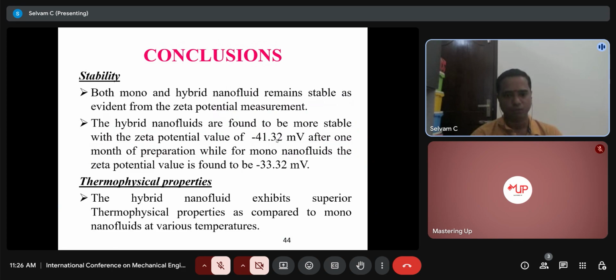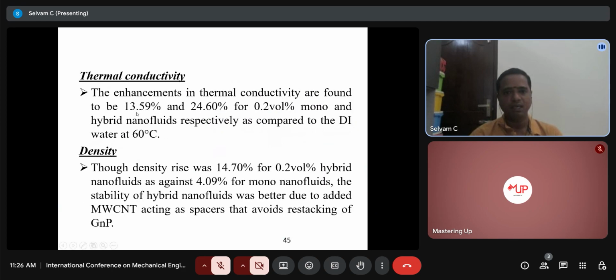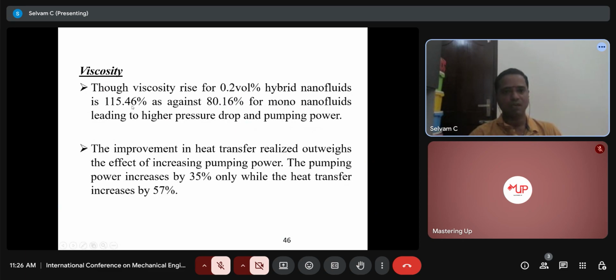With respect to thermal conductivity, we observed 13.59 percent with the GNP alone, and with the use of hybrid, 24.60 percent. Density is also increased. Actually, density should not increase more, but we observed a higher density value with the hybrid nanofluid: 14.70 percent, while it is less in the mono nanofluid, 4.0. With respect to viscosity, we observed 115.46 percent with the hybrid nanofluids, while it was up to 80.16 percent for the GNP nanofluid.